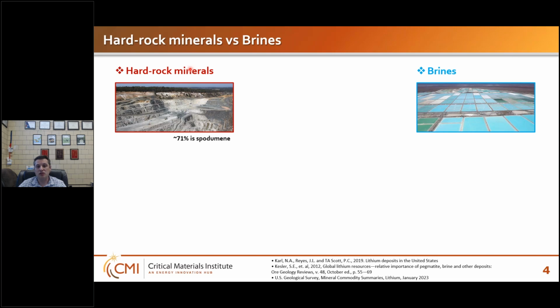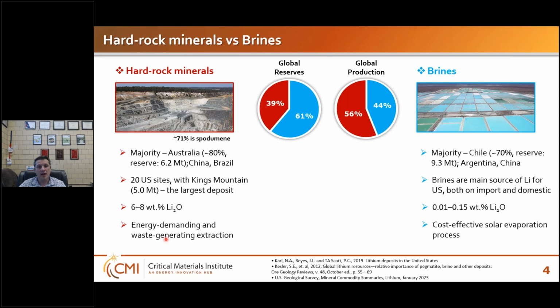The main process that is being used in industry is the so-called sulfuric acid roast, where they take beta spodumene and digest it with concentrated sulfuric acid at 250 C. Another approach that is adopted by industry is the soda ash process, which is basically hydrothermal at high pressure and temperature with sodium carbonate to get to a battery grade lithium compound. The approach we are developing is mechanochemical extraction of lithium at low temperatures, or simply MELT process. Our approach allows us to use alpha spodumene directly, thus omitting this energy intensive decrepitation step. With our approach, we use much milder conditions to extract lithium and get battery-grade lithium compounds.